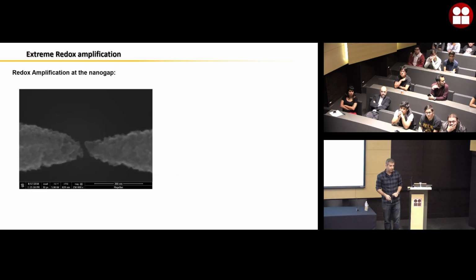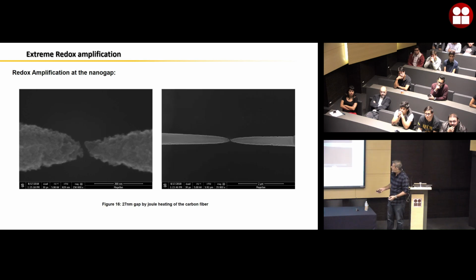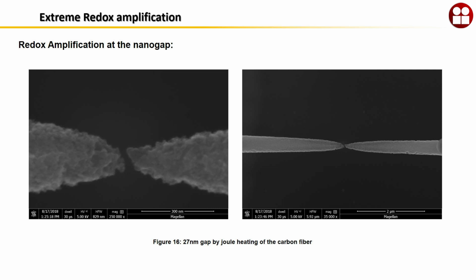Our solution is a nano gap. How do we make these? We make the same electrode with the lithographic process. We lay a nanofiber on the carbon electrode, right? Then we passivate the whole system, the whole fiber and the microbands, with silicon dioxide, because we want the electrochemistry to only happen at this gap, right? And at this point, we put the electrode inside a vacuum or nitrogen chamber, and then apply potential, and because of the Joule heating, it heats up. Silicon dioxide, you see the small ball here, sublimates, and it creates a small crack here. And that's all I need to do for extreme redox amplification in the nano gap.